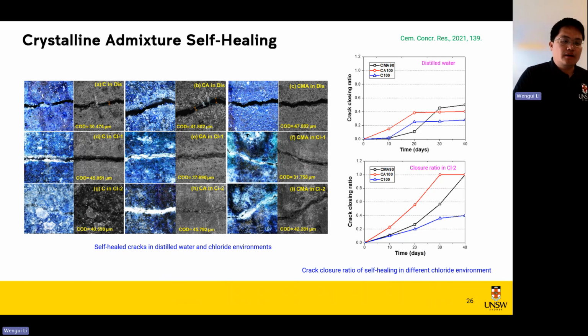So in terms of the crack duration, we found chloride solution is more effective for the self-healing compared to the distilled water. For example, after 8 wet-dry cycles, we found the cracks in the chloride solution exhibit 100% closure, while those in distilled water presented only 40% crack closure.